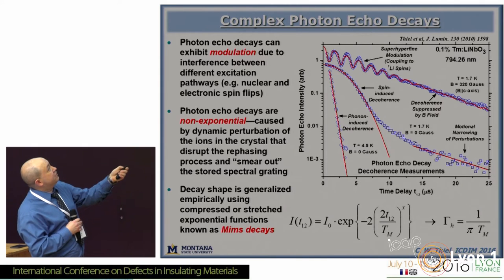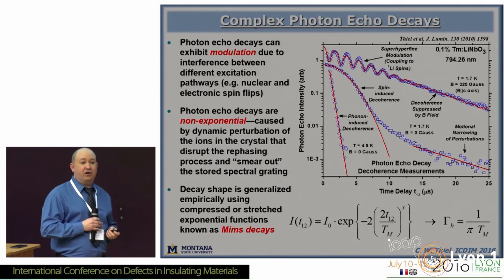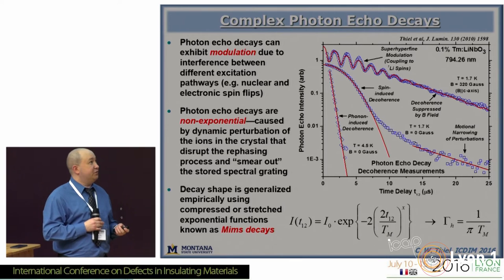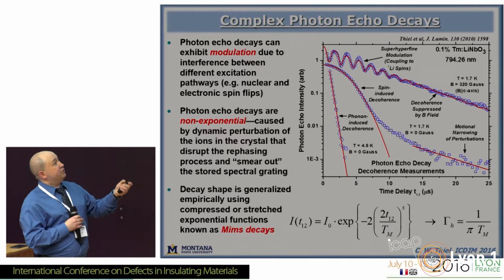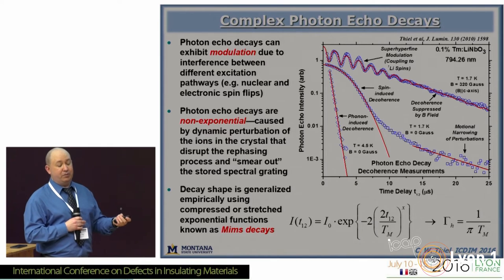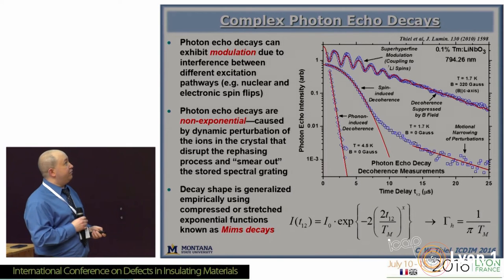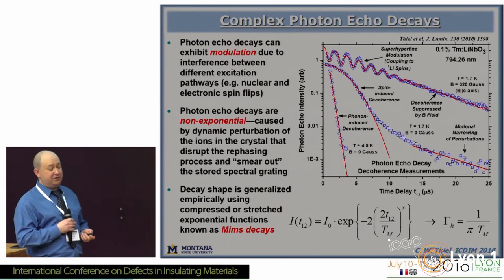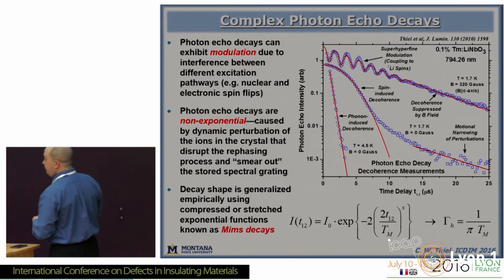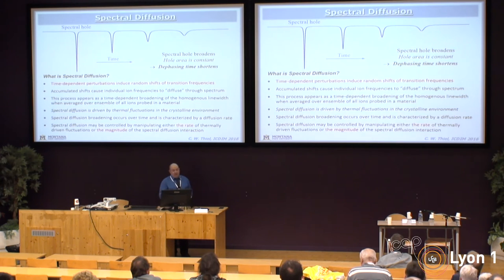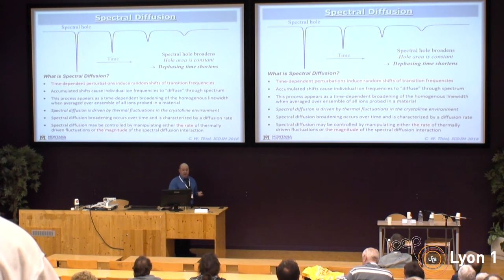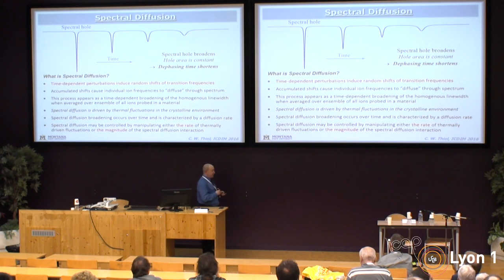This is a very simple picture of spectral diffusion in the time domain. Initially, we have all these ions with the same homogeneous line width. Because of perturbations in the environment — different for different ions at different places in the crystal — that homogeneous ensemble begins to broaden into a wider packet. Some ions go one way, some go the other way, meaning their collective phase information is lost. Over time, the spectral information stored is lost. This can be driven any time the rare earth ion couples to an environment with associated dynamics, whether that's electron spins, movement of defects in the lattice, or movement of electrons in the lattice.